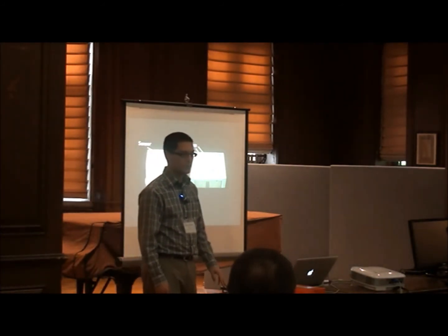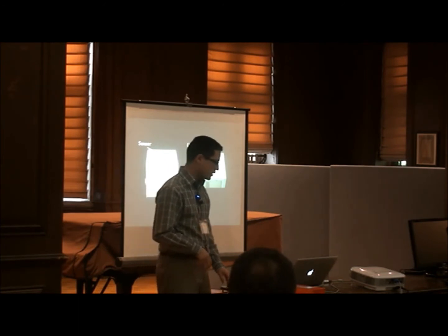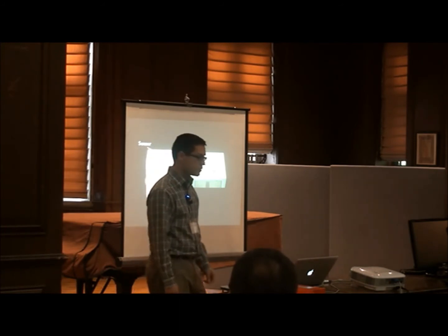So at its core, we have a system that uses a single camera and multiple lights to measure 3D. There are lots of ways to measure 3D structures that come out of the computer vision or machine vision literature. In fact, we could use almost any of them, because fundamentally, when you press a piece of gel into the surface and you remove its optical properties, you can use any kind of machine vision at this point. Structured light, laser scanning, multi-view 3D measurements with multiple cameras. The one we've chosen for a lot of what we do here is a single view, multiple light source approach called photometric stereo. It has advantages for measuring very fine scale surface features. Literally, you get a measurement at every single pixel in the image, and when you have an 18 megapixel camera, that gives you a lot of surface detail.